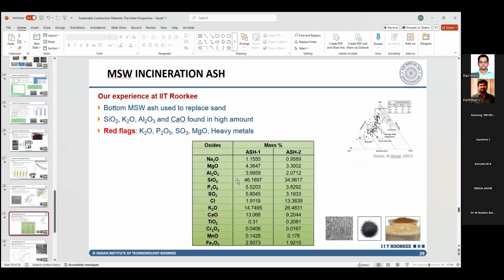So when we have been trying this out, in our case, we got ash from, I think, one of the plants in Sonepat itself, and what we found was the bottom ash is very high in silica, alumina, and calcium, but also in phosphorus and alkalis. And that's a big red flag. We don't want these materials, heavy metals, sulfates, in our construction material that's eventually going to end up in concrete. So that is a challenge.